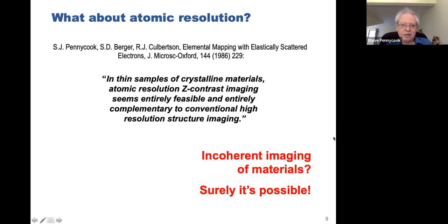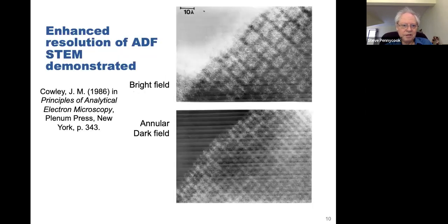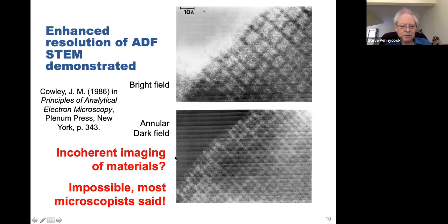Well, this was '86 and unknown to me at the time, this was when we did not have internet, but John Cowley at ASU actually had an HB5 with a high resolution pole piece. It was not a VG microscope's pole piece. It was a JEOL pole piece actually, but he produced this pair of images and he commented that the annular dark field image shows the expected increased spatial resolution. And that's basically what he said. And he didn't mention, although he must have changed the focus, this is a phase contrast image. This will reverse contrast, as you know. This would not have changed contrast. But he didn't say anything about that, which is kind of surprising. And I never really talked to him about that.